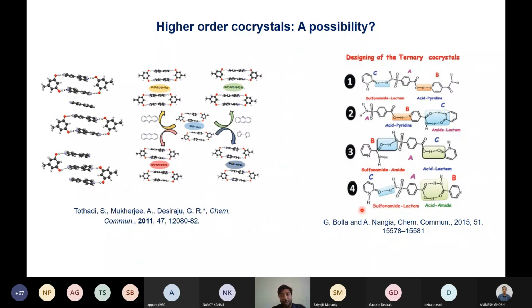So this is the last part I'll talk about. Through this study, we also obtained a bipyridine co-crystal, and we used shape and size similar molecules to replace that to get ternary co-crystals. Now the question is whether this is really feasible in the pharmaceutical space. Recently one paper from Professor Nangia's group has shown this possibility of ternary co-crystals using pharmaceutically relevant molecules. And if you have read the last few papers of Professor Desiraju in Molecular Pharmaceutics, or attended his talk in Bradford, you'll see that he advocated for inclusion of co-crystallization in the manufacturing stage rather than at the formulation stage. If that becomes a possibility, then I think these higher order co-crystals will be more prominent in pharmaceutical space.